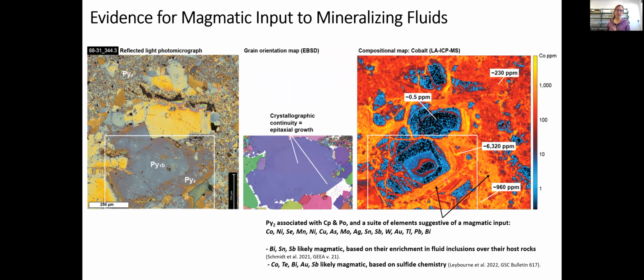Now, if we look at some of the other compositional maps, which aren't shown here, I can see that the high cobalt is also associated with other metals like bismuth, tin, and antimony. Previous studies by Schmidt and Leybourne and others have shown that this particular suite of metals is typical of magmatic influence. So it looks like our pyrite 2, those overgrowths, probably formed from hydrothermal fluids that had a magmatic input.